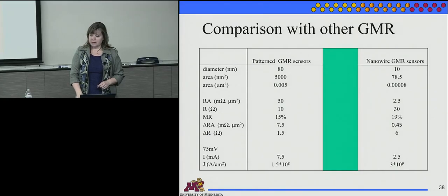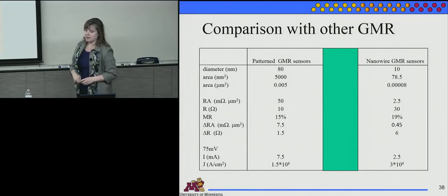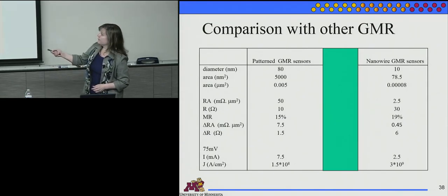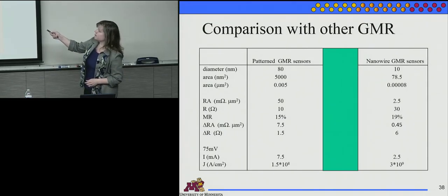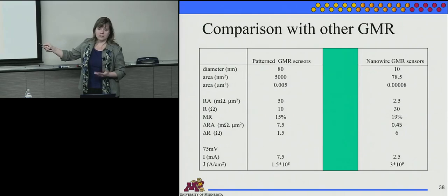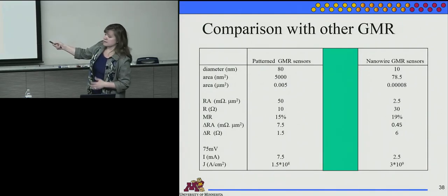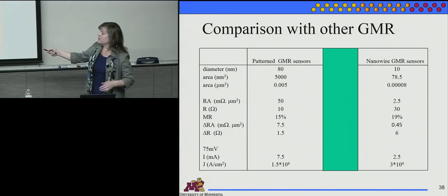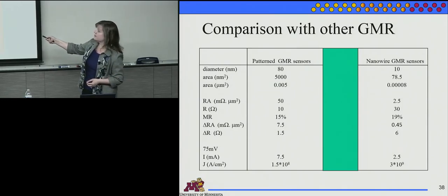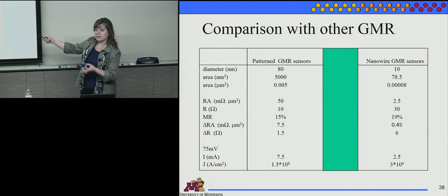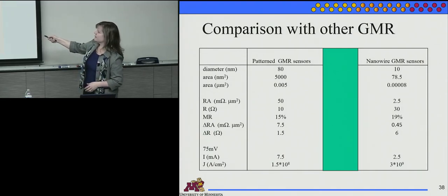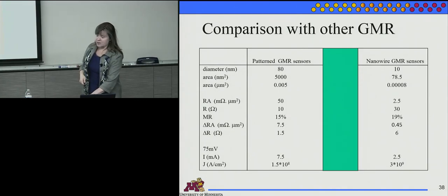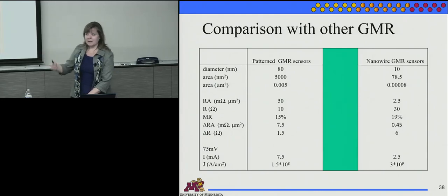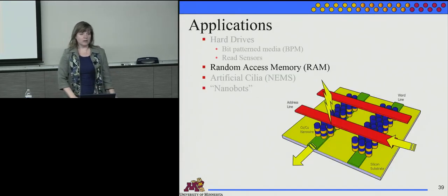All right, comparison with other GMR. These are mostly Heusler alloys that we end up comparing to. And anyway, you can just see what matters is the area should be small, diameter small. The RA product should be small. That's a unit they go off a lot with these sensors. A TMR would have much higher resistance, so they're trying to go to all metal, so they have lower resistance in the read heads. We get about 30 ohm resistance in the actual stack itself. It's actually 19% MR, and these are actually, I guess, very high. Remember, you want a high switching current density for read head, and so all those parameters look like they could make pretty good read sensors.